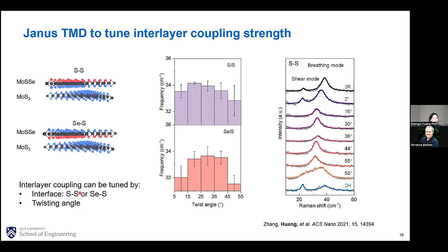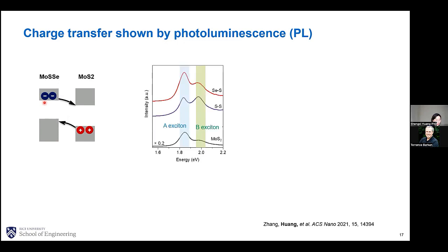In addition, the difference between the SS interface and Se-S interface can also be seen by the charge transfer and photoluminescence spectrum. So we know that if we stack a MoSSe layer with MoS2, because of the band alignment, there will be charge transfer between the two. This charge transfer can actually be seen by the photoluminescence spectroscopy shown over here. So we can see for monolayer MoS2, we can typically see two excitons, A exciton and B exciton.